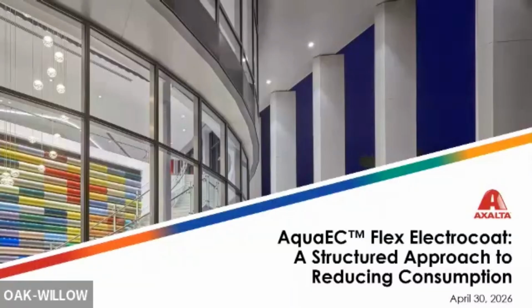So a standard Ecoat coating does not protect, it will not cure in some of those areas. Some of those deep recessed areas would not cure. So we had to change our thinking and move to something that we call broad bake Ecoat. So I'm going to use broad bake, low bake, and expanded bake interchangeably.